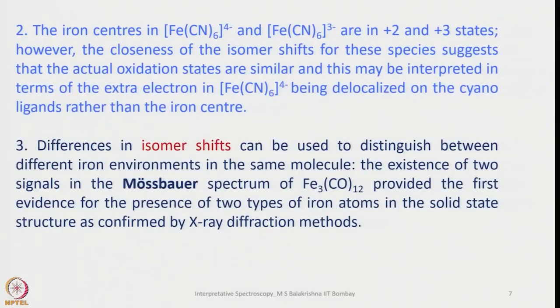So the existence of two signals in the Mössbauer spectrum of Fe3(CO)12 provided the first evidence for the presence of two types of iron atoms in the solid state structure, as confirmed by the X-ray diffraction method. If you just look into the structure of Fe3(CO)12, we have two bridging carbonyls here. The rest will be different. So this we should remember.